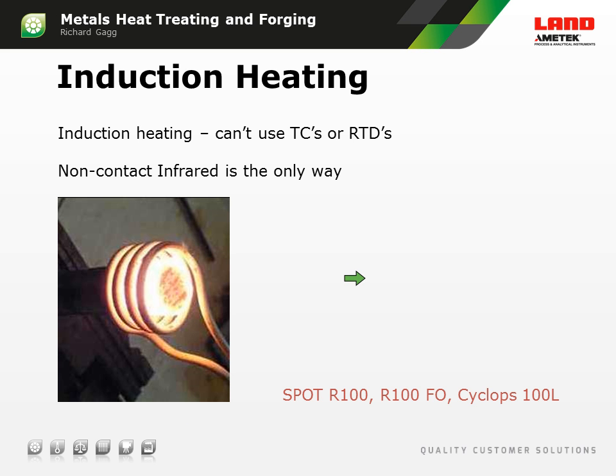Again, you cannot get anywhere close to this with a thermocouple or an RTD because it would be excited by the RF field and it would be unable to make a measurement. So in these particular cases, we typically use a ratio thermometer, which would be very good because it doesn't need to see the full spot size fully filled. We can look at a partially filled target with a ratio thermometer and get a very accurate reading. So for instance, the Spot R100 or the R100 fiber optic. And if you're looking with a portable, the Cyclops 100L would be very good to see through the gaps.